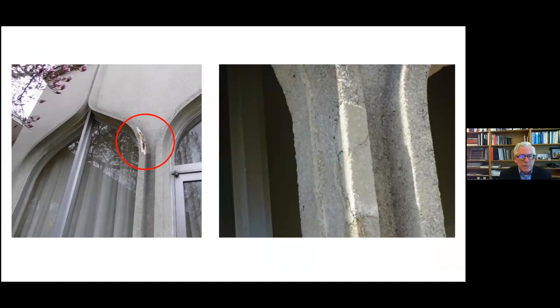So as far as the investigation, we also found that areas of the double curved ribs seemed to produce more of the deterioration. And there were different attempts at repair in the past, some of which were marginally successful, but some of them had continued to deteriorate and delaminate at corroded reinforcing steel.